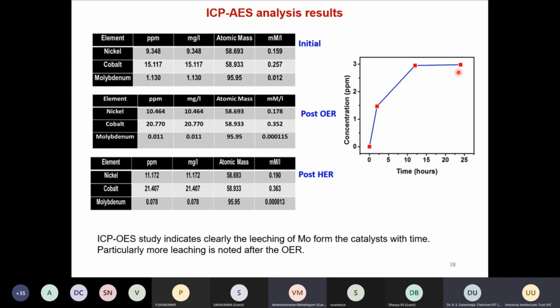This is something very interesting, which leads to the activity, because once the molybdenum leaching happens, it creates a lot of pores in the catalytic material. So what is very important is that the electrolyte can now reach the bulk of the material instead of only the surface of this material. We found this is one of the major reasons for the better catalytic activity of this material: the molybdenum leaching, which increases the number of active sites that the electrolyte can reach.